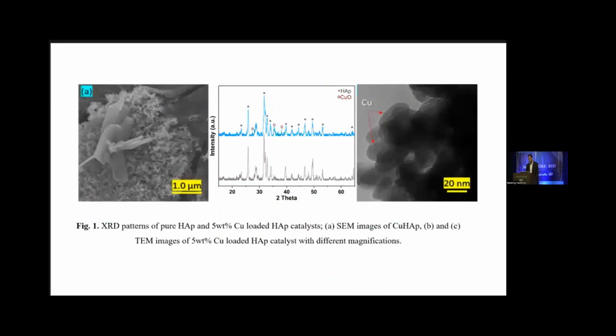So this TEM is showing the formation of copper nanoparticles in the range of 20 to 30 nanometers. And this is the XRD of the copper oxide that has been constructed on the hydroxyapatite.